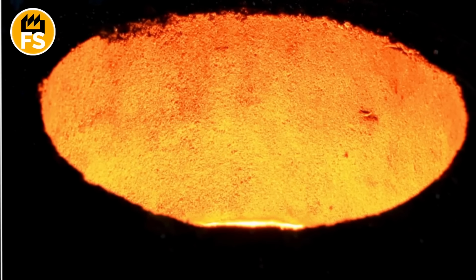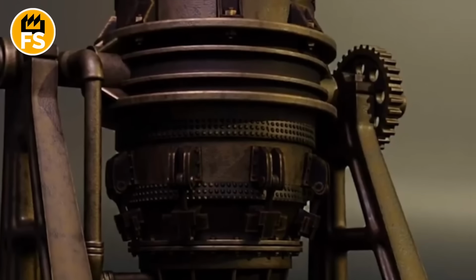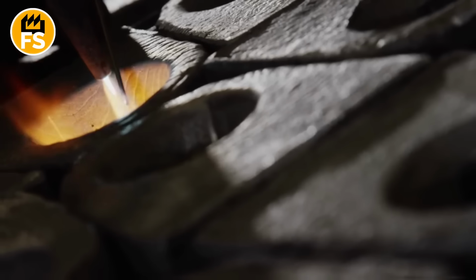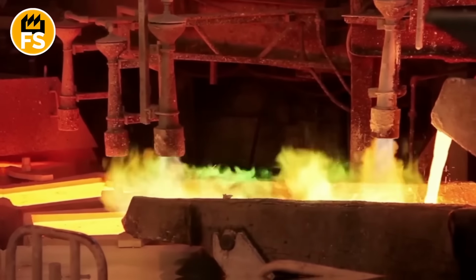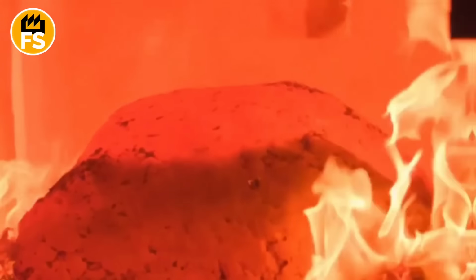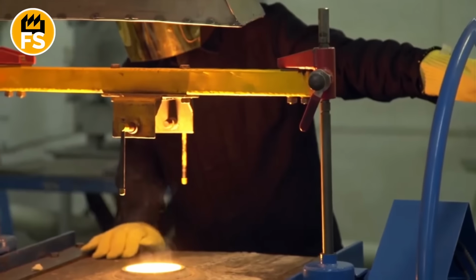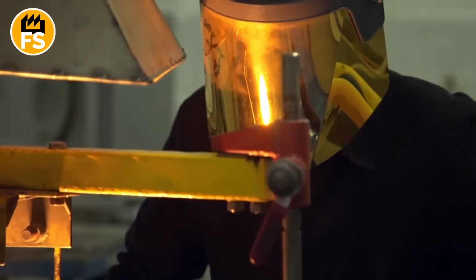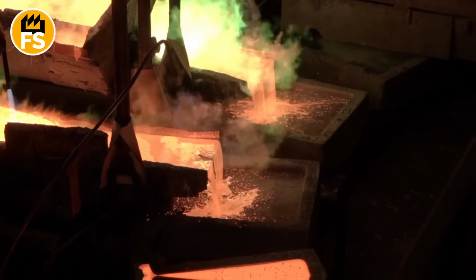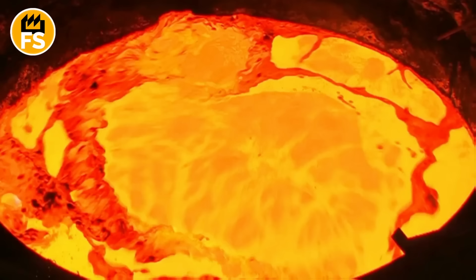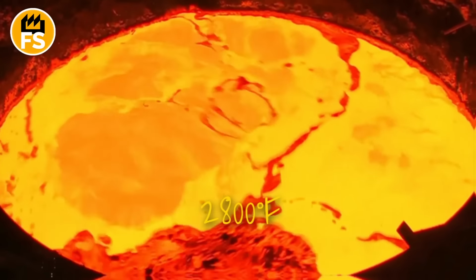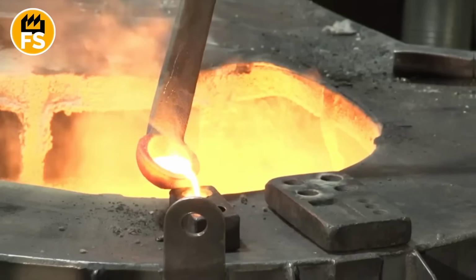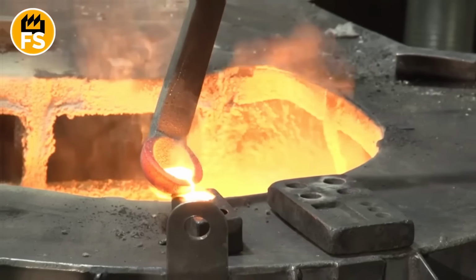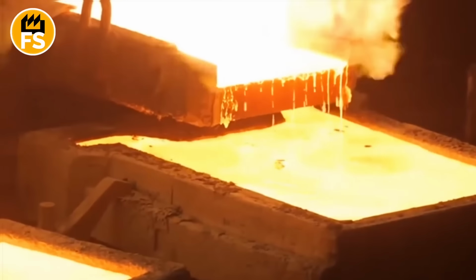Next, the powder or palladium sponge is fed into melting facilities. Most commonly, induction or electric arc furnaces are used, where the metal is heated in crucibles made from inert materials. The atmosphere inside the furnace is monitored especially carefully. Argon is introduced, or the space is evacuated to prevent oxidation and losses. The temperature is gradually raised above 2,800 degrees Fahrenheit until the palladium particles fuse into a uniform molten mass with a mirror-like surface.